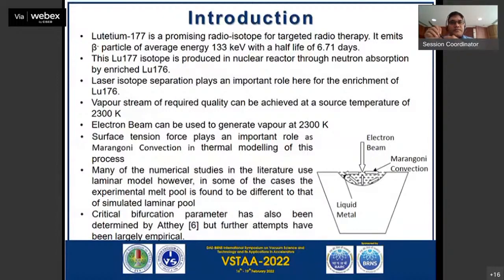Now, in laser isotope separation, we have to generate a vapor stream. That vapor stream will be generated from the source at a temperature of 2300 degrees Kelvin. For generating a vapor at 2300 Kelvin, electron beam evaporation can be used. It is a well-known evaporation process, which will be carried out in high vacuum.